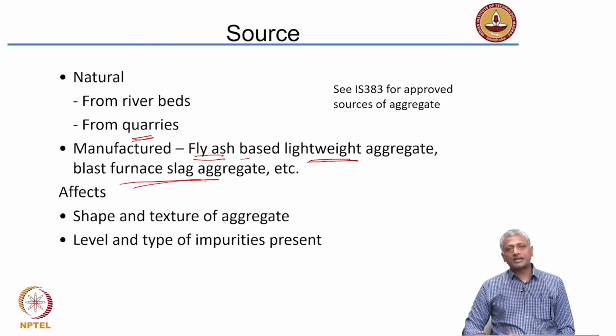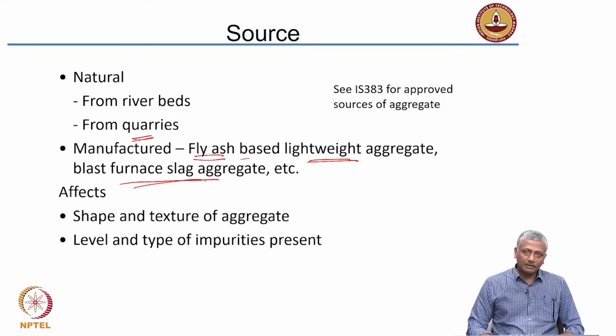Many of you are aware of this blast furnace process where pig iron is obtained. So, we add limestone as a flux to reduce the temperature, and that causes the calcium oxide in the limestone to combine with the impurities in the iron ore in the form of silica and alumina and float on top of the iron as slag. And that slag, if you cool it it becomes solid, and then when you crush it to aggregate size, it becomes a blast furnace slag aggregate. Okay. So, you need to be aware of natural sources and manufactured sources.